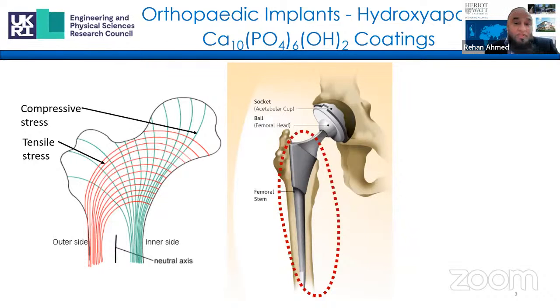There are a number of attributes which make up the desired structure and properties of hydroxyapatite coatings. Some of these include correct level of porosity, calcium to phosphorus ratio, the ratio of the crystalline to amorphous phase, the adhesive strength of the hydroxyapatite coating, etc. And although the US Food and Drug Administration do not require a residual stress profile in thermally sprayed coatings for the approval process, through thickness residual stress profile plays an important role dictating the desirable characteristics in the implant.